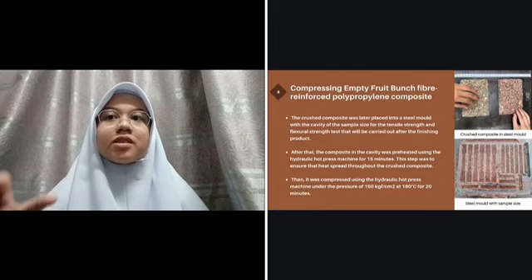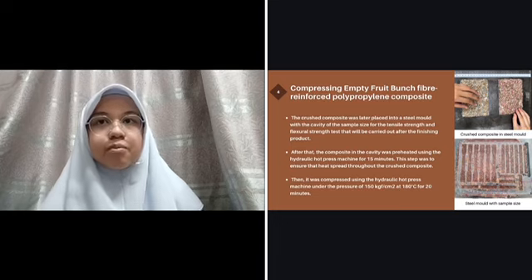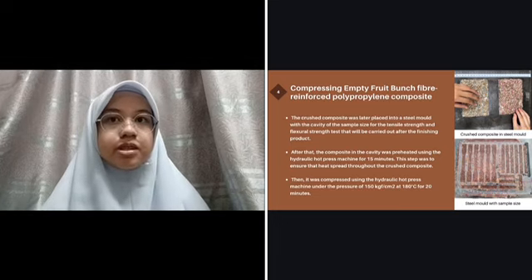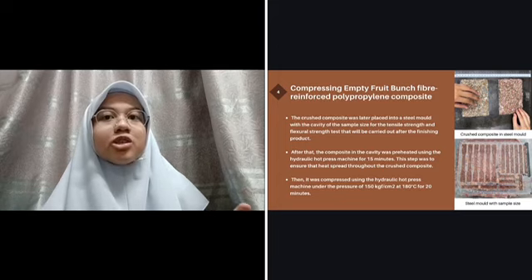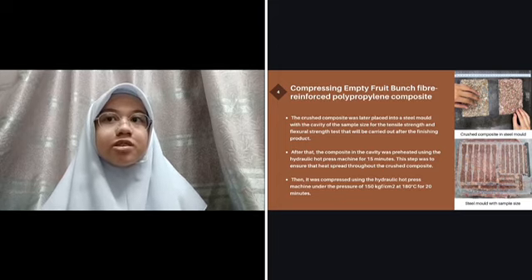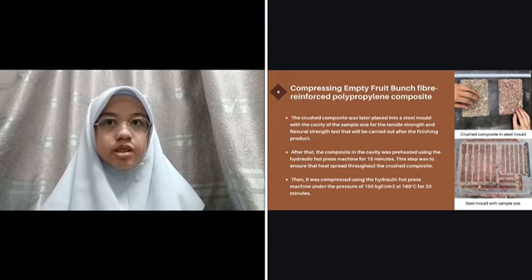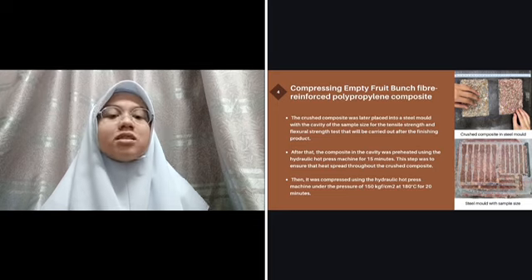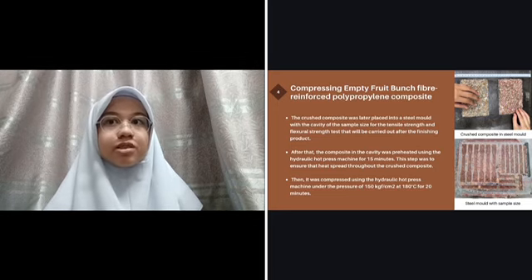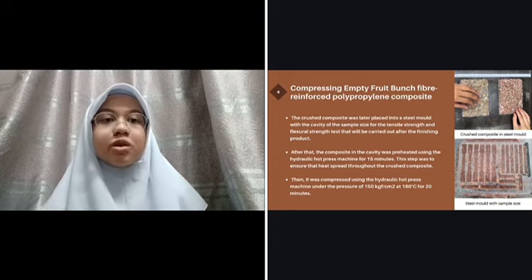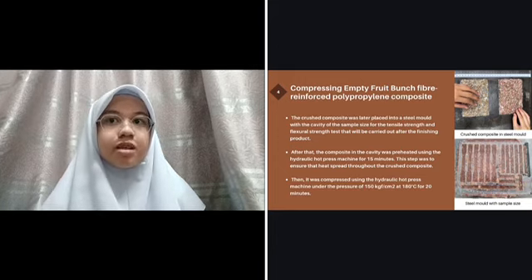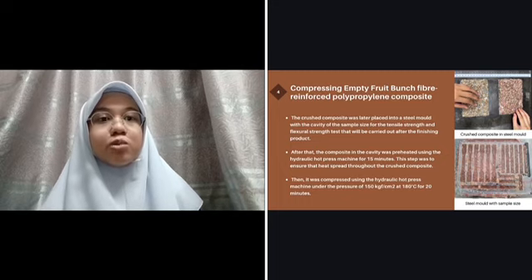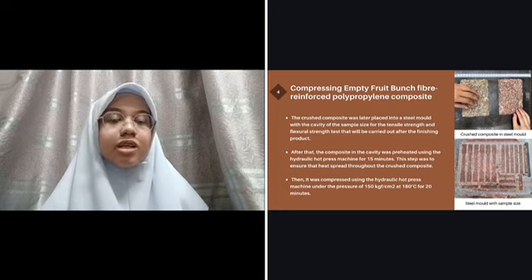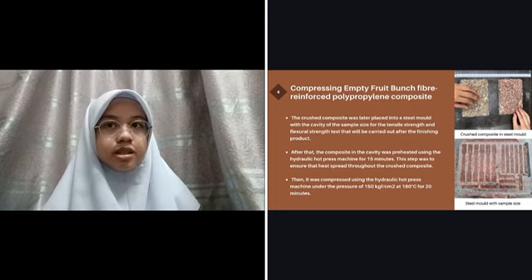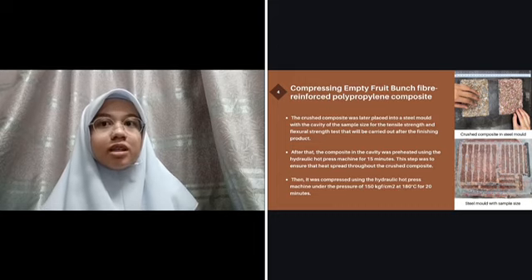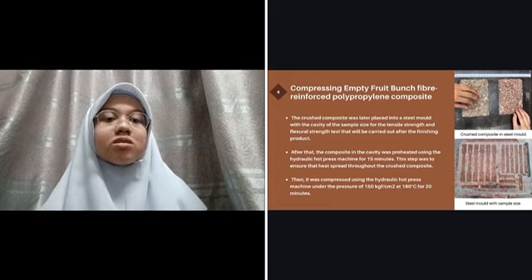And last but not least, the process of compressing the empty fruit bunch fiber reinforced polypropylene composite. The picture on the upper right shows the composite that was crushed. Firstly, we put the crushed composite in the steel mold that has the sample size for the tensile strength and also the flexural strength test that will be carried out after we obtain the final composite panel. After that, the composite in the cavity mold will be preheated using the hydraulic hot press machine for about 15 minutes. This step was done to ensure that all the heat was spread thoroughly through the crushed composite.